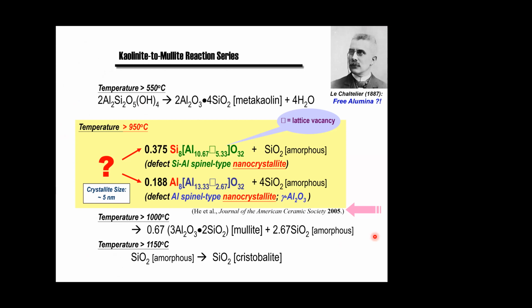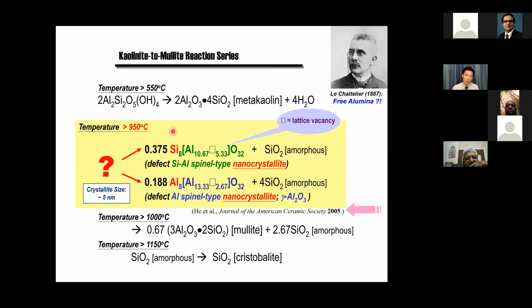This is a very simple and traditional process in the industry, but its scientific mechanism, in fact, is still very complicated and not necessarily fully understood. For example, if you heat the clay to 950 degrees Celsius, you may basically generate 2 types of what we call defect spinel type of structure. And both of them are so-called nanocrystalline. You can either have the silica sitting at tetrahedral sites, or even have aluminum sitting at tetrahedral sites. If you have aluminum sitting at tetrahedral sites, in fact, this is what we call gamma alumina as the material.